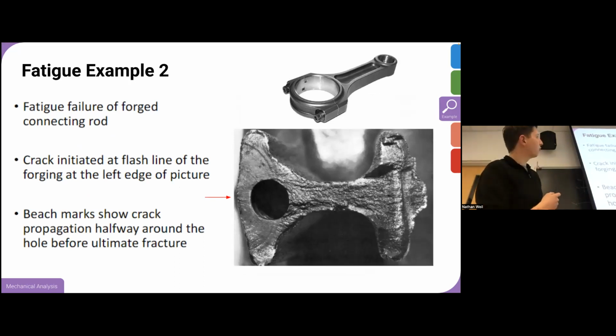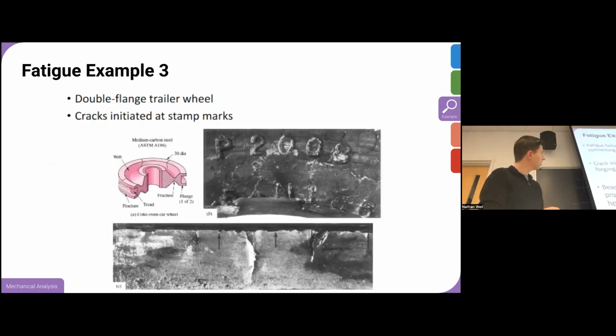Another example, this is a forged connecting rod. I'm not sure it's forged, it looks pretty cast, but whatever. It's not post-machined, that's for sure. In this case, the crack initiated at the flash line between the parts of the mold. Then it propagated across, and you can see it didn't take very long because engines have high loads. The crack got a little way, and then it almost failed immediately because it had to get past the oil passageway, and then you lose this whole side of the I-beam in the oil passageway support, and the rest of the material can't handle it, pops. It also got halfway around the hole, which is kind of interesting, the oil passageway.